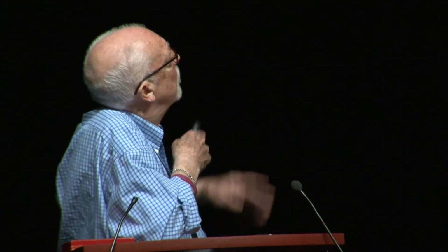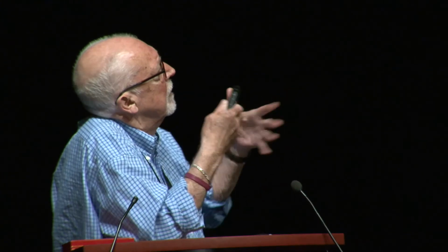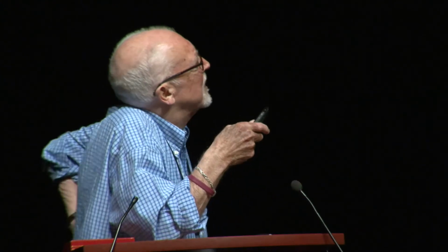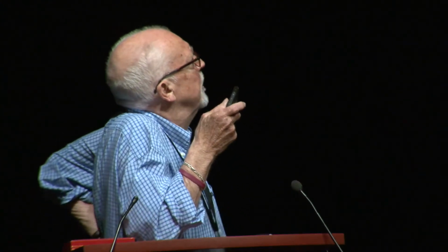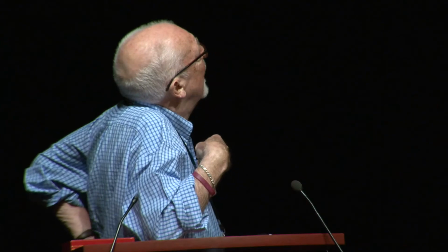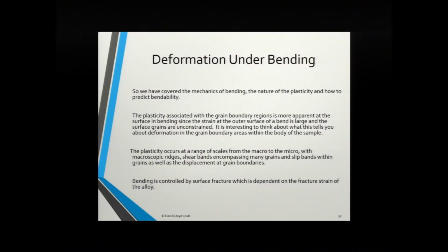Okay, so we've covered the mechanics of bending, the nature of the plasticity, and how to predict bendability. And I think we can do that all fairly well in a self-consistent fashion. The plasticity associated with grain boundaries is more apparent on a bending surface than it is generally, and the strains locally at grain boundaries can be very, very high. And that's a result of the unconstrained deformation of the surface.